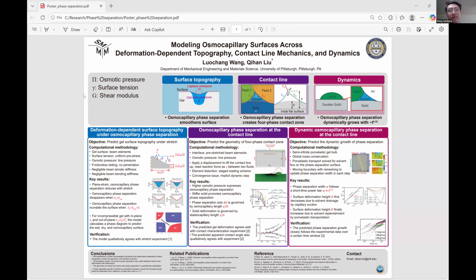The key phenomenon here is the phase separation at the surface. Imagine a swollen solid, such as a jelly, hydrogel, or tofu. They can locally exude solvent outside from the surface, creating a small solvent region that is called the phase separation. This locally separated solvent region can change surface shape, can modify the contact line geometry, and can also evolve with time. Our goal is to build one computational modeling framework that predicts how deformation changes the surface topography, what geometry forms at the contact line, and also how the phase separation zone grows over time.